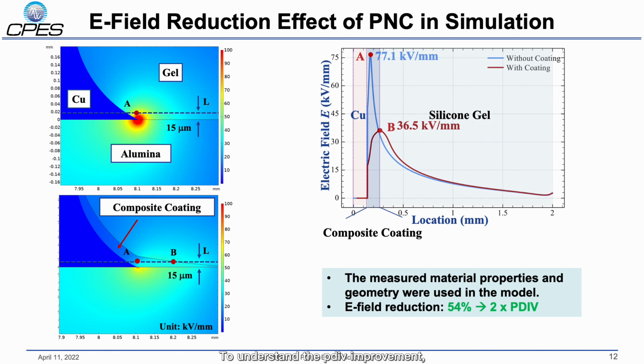To understand the PDIV improvement provided by this PNC material, we did some E-field analysis to find out the E-field reduction effect of this PNC material. These two pictures show the E-field distribution around the triple point. The top one shows the triple point without coating, and the bottom one shows the triple point E-field with the coating.